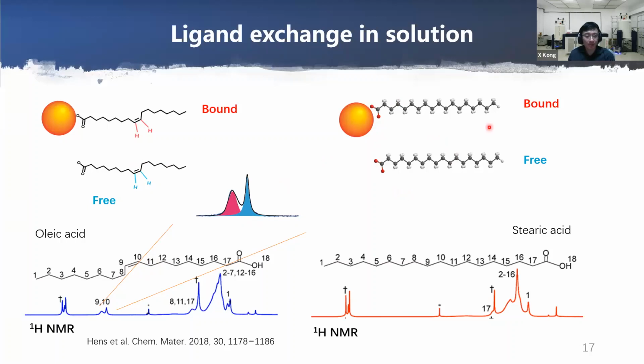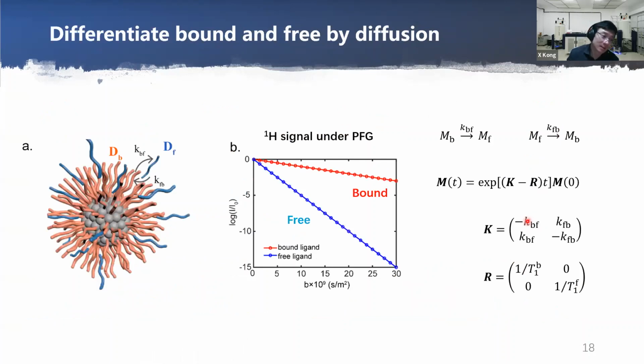However, in more general cases, the ligands don't need to have a double bond. They can be all saturated carbon hydrocarbon chains. So for example, here, the signals of these hydrocarbon chains in solution will strongly overlap. So we cannot separate from the chemical shift whether they are bound or free. But there are other ways to distinguish the signals. And we think probably the diffusion coefficient is the most convenient way to distinguish the free and bound ligands.